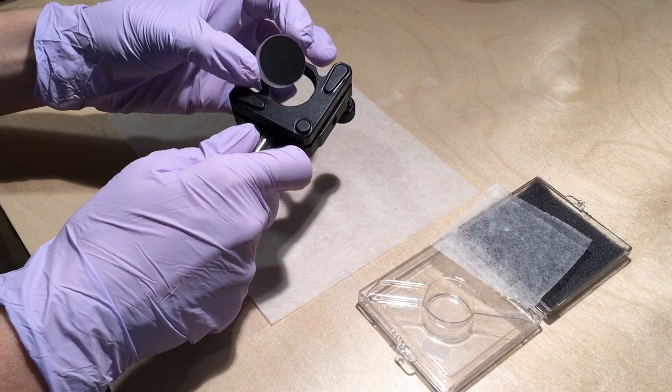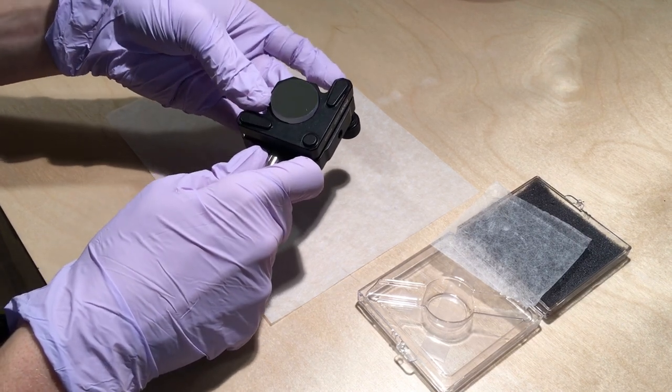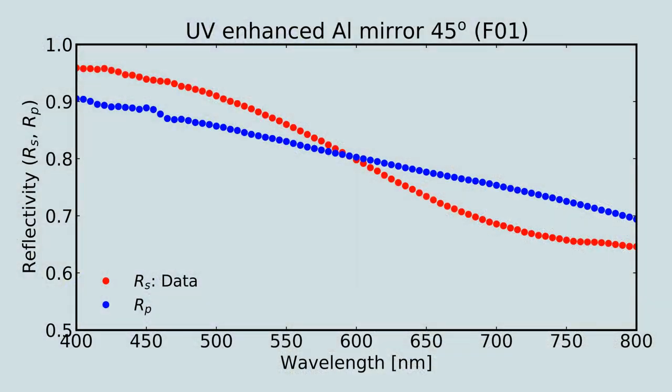We tested a magnesium fluoride coated mirror, which the manufacturer designates UV enhanced aluminum. Of the mirrors we tested, this mirror has the best reflectivity at 400 nm.